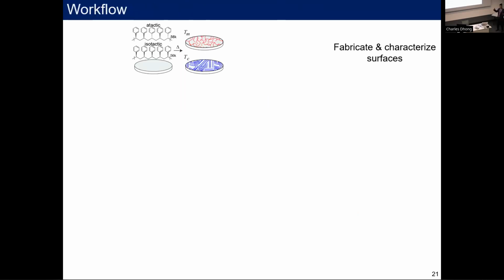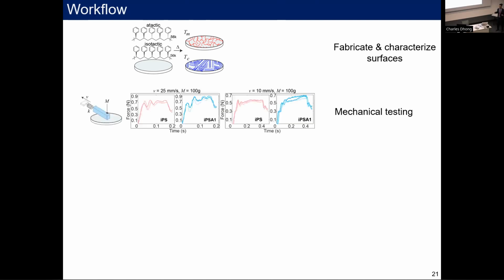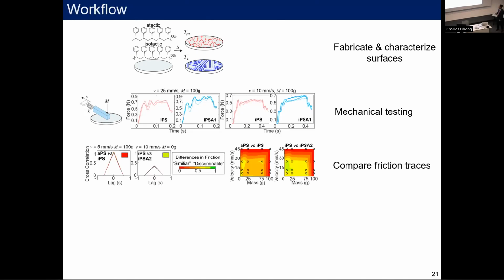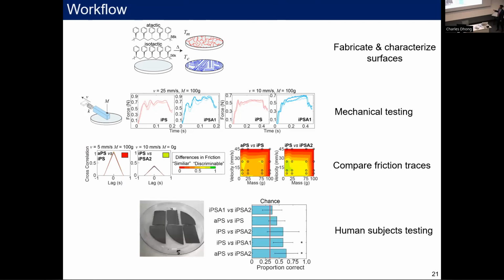And so we have this workflow, right? So we make our samples, we characterize them through traditional ways. We do our mechanical testing to give us an idea of which ones may feel different. So in this case, my list was pretty small, so I probably could have tested them all. But right, if I want to test 10 materials, then this will become critical. Then we compare our friction traces and basically do our human subject testing. And here we start to see that people can tell surfaces apart even by their degree of crystallinity.